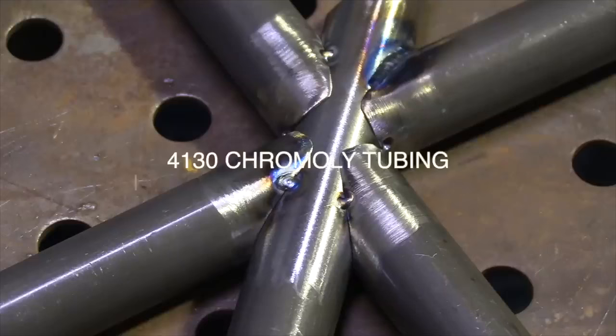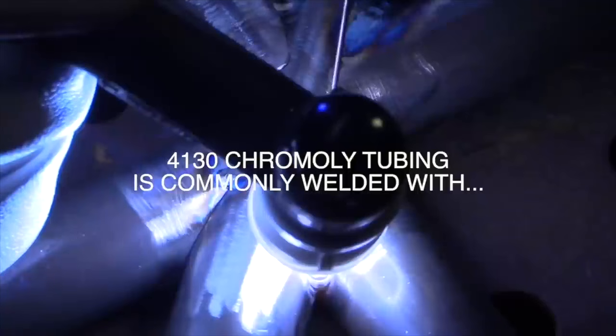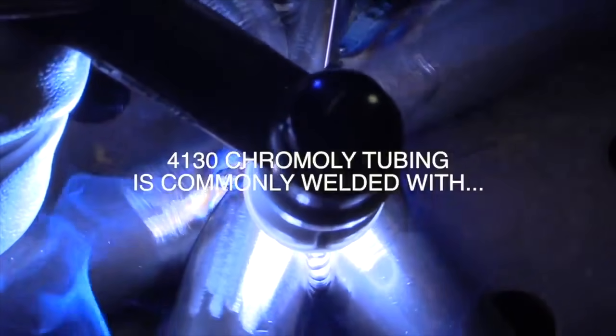One of the main considerations when you're welding carbon steel, especially if it's got a lot of carbon in it, like say medium carbon steel and above, or even chromoly, is that as it cools, if you heat it up hot enough past the transition temperature and you cool it quickly enough, it will harden. It'll get brittle. You don't want that. So it's good to think about whatever the main concern is with each metal. And with carbon steel, one of the main concerns is getting it too hard and brittle by quick cooling.